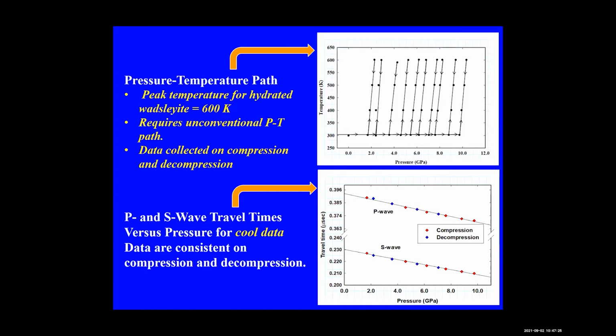So back at room temperature, we again increase the pressure. We reheat the sample to 600 K and repeat the data collection process. In all the experiments that we've done, we also try to collect a few data points on the way back, that is on decompression.